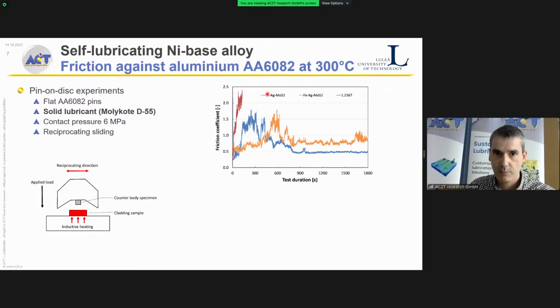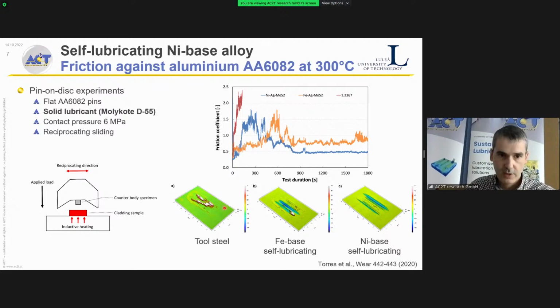And with the nickel base, the blue line, we see that initially friction is low due to the solid lubricant, then you end up building a tribofilm, and at some point friction gets very stable with a value of 0.5 and could continue during a much longer period. And also in this case, we see that we switch from adhesive wear to mild abrasion.